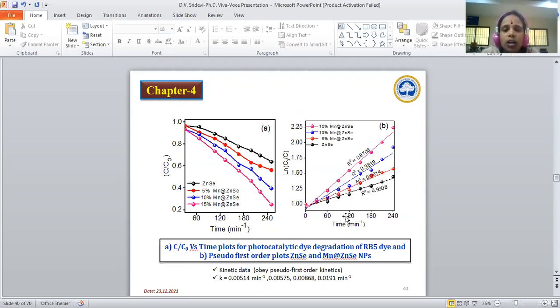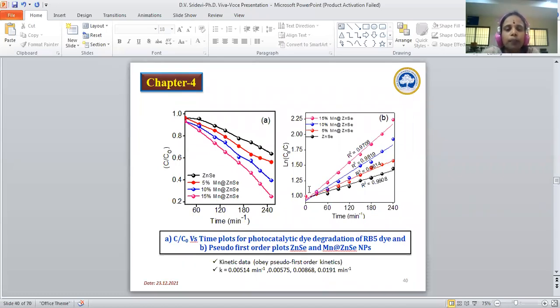Figure B shows the kinetic plot of zinc selenide and manganese doped zinc selenide nanoparticles. A straight line shows all the synthesized nanoparticles exhibit pseudo first order kinetics. The apparent rate constant values for zinc selenide is found to be 0.00514 min^-1, and 0.00575, 0.00868, 0.0191 min^-1 for 5, 10, and 15% manganese doped zinc selenide nanoparticles respectively.